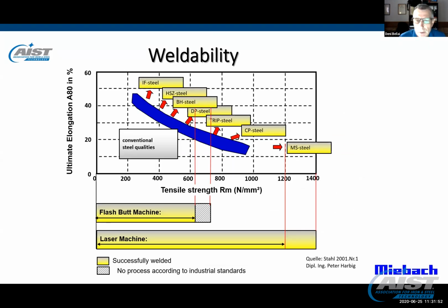Let's start with weldability. Laser welding enables the coil joining process to weld the widest variety of steels. It's the most capable process for joining different steel grades and cross sections to one another. It can weld hot band or tin plate and all varieties of finished products in between. The process itself is minimally disruptive due to the very small heat affected zone. It is very conducive for inline heat treatment, so as to maintain ductility in the weld with a minimum disruption of the cycle time.